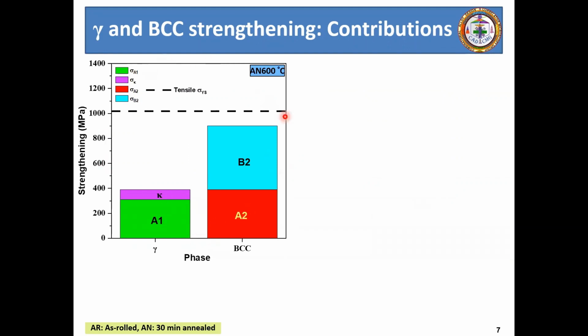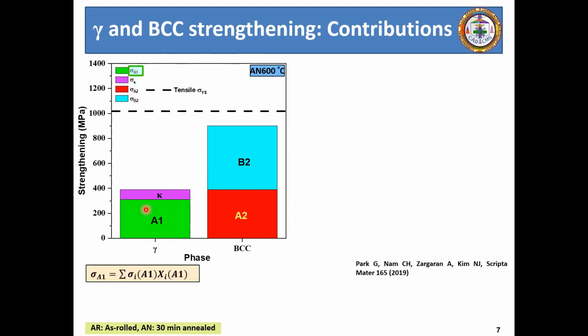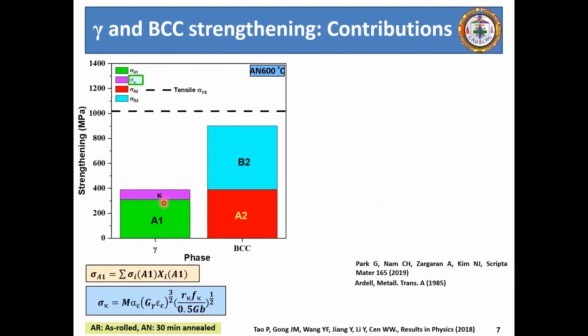So then, having now known this, I'll be further discussing the contributions of the different phases towards influencing the overall strengthening. For example, if you look at a 600 degrees annealed condition, where the dotted horizontal line represents the uniaxial tensile yield strength, what we can clearly observe is that the sigma A1 here basically represents the solid solution strengthening contribution from the gamma phase, and then the sigma kappa here represents the strengthening contribution from the nanoscale kappa precipitates localized within the disordered gamma phase.